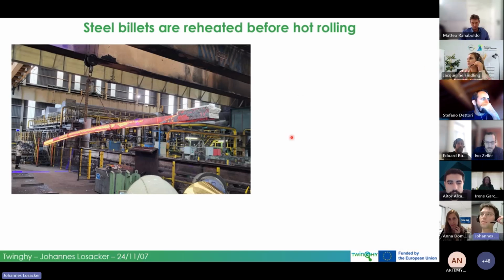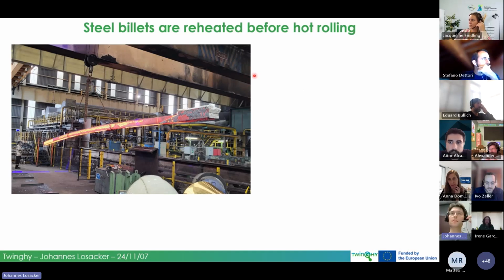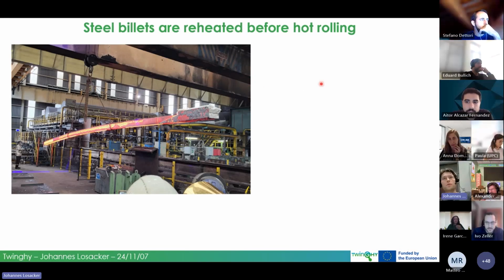This time it's not about the electric arc furnace, but rather about the reheating process of steel, which takes place at the hot rolling mill. Here in this picture, you can nicely see a heated billet. It was heated in the walking beam furnace in Celsa 3 that you see in the background. Here we did some special measurements, which is why it is about to be removed by a crane. Usually this reheated billet will just stay on the roller table and go straight to the hot rolling mill, where it gets its final product shape.